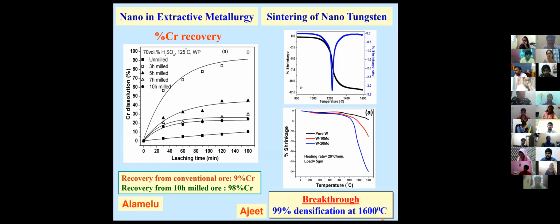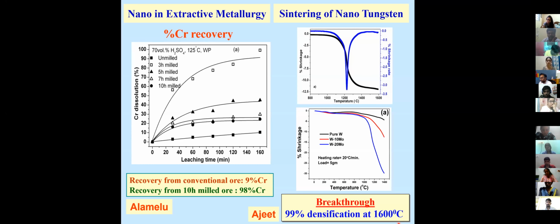There is a plant called the heavy alloy penetrator plant, where they make tungsten pieces. What they do is simply take these pieces and throw them onto enemy tanks. They are called kinetic energy penetrators. Defense people use them for that purpose. Simply like a bullet, it will go, because half mv square is the kinetic energy of anything. And if the mass is higher, then the energy is higher. When will the mass be higher? For a given volume, if the density is higher, the mass is higher. Tungsten has a density of 19.3, whereas aluminum has a density of 2.7. So instead of an aluminum piece, if I throw a tungsten piece, it will have a much higher energy. And this is exactly what they do.